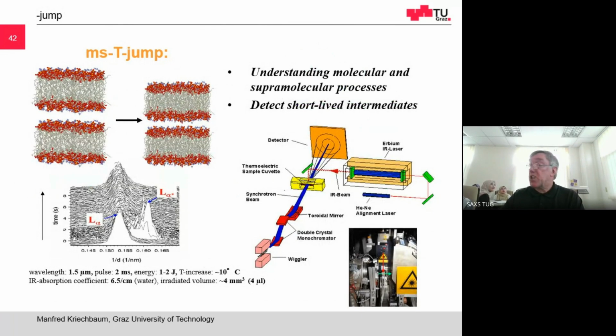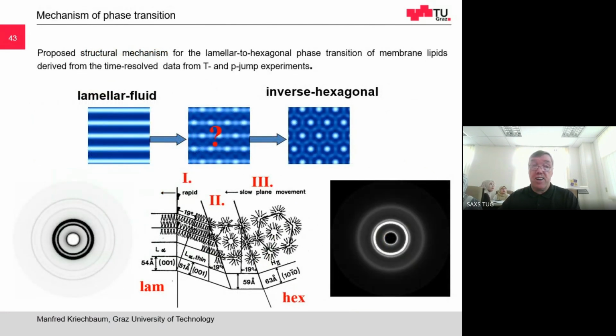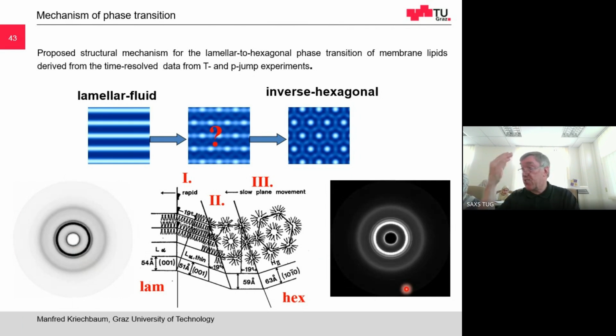You can also do jumps instead of small pressure or temperature changes, so you can apply a laser jump. In that laser jump, you heat up your sample within milliseconds, about 10 degrees, so you can make a phase transition within, let's say, 5 milliseconds. You can induce a phase transition. Here are some examples. So lamellar phase, hexagonal phase. This is cycling hexagonal phase, lamellar phase. This was done at a synchrotron with millisecond time resolution.